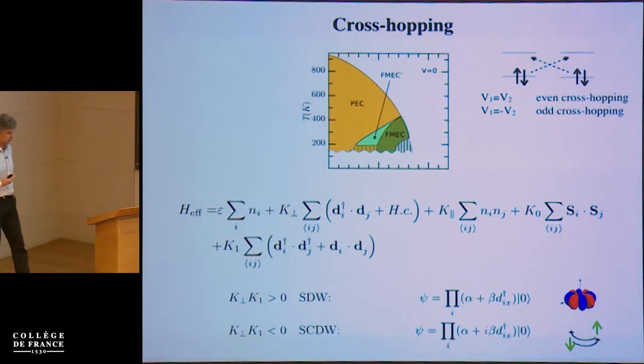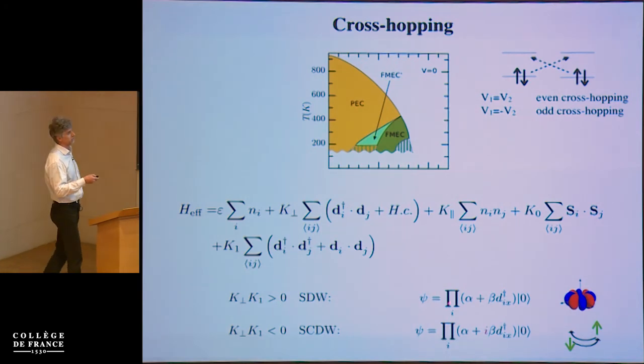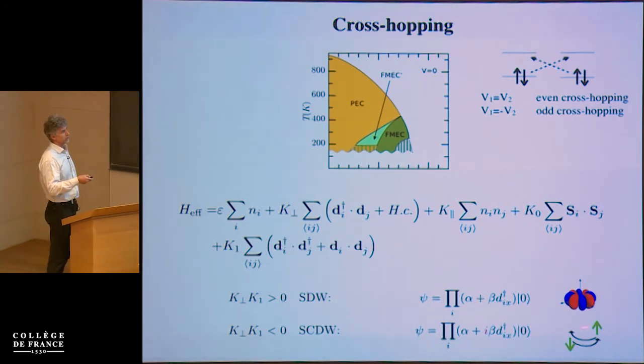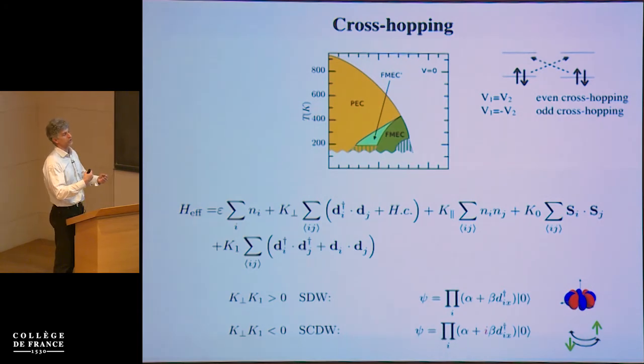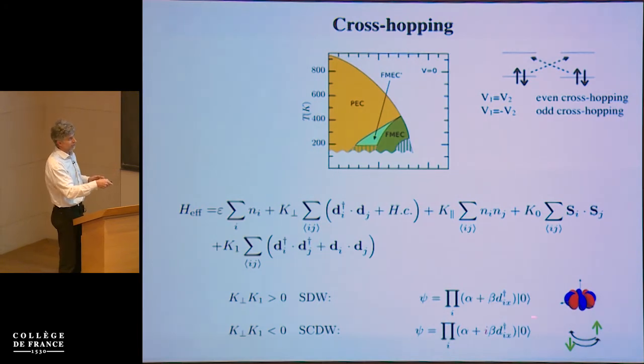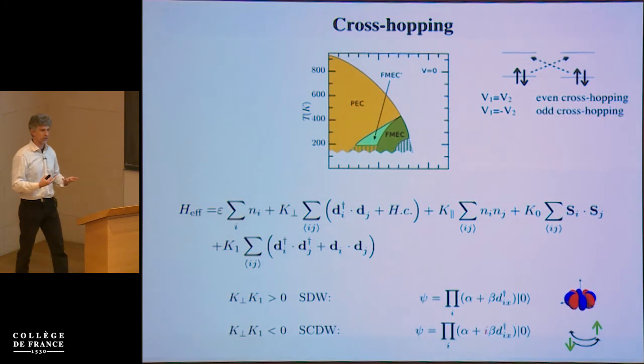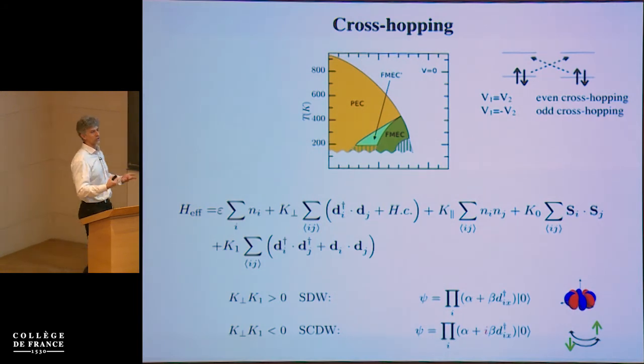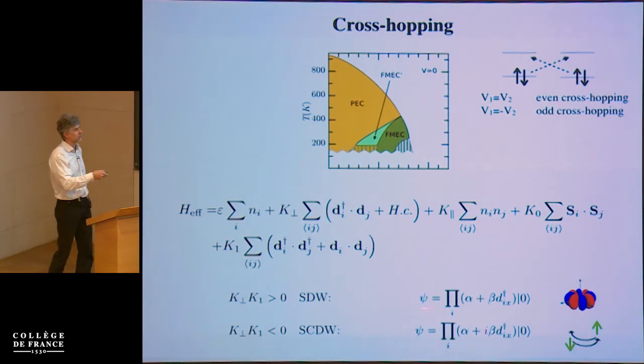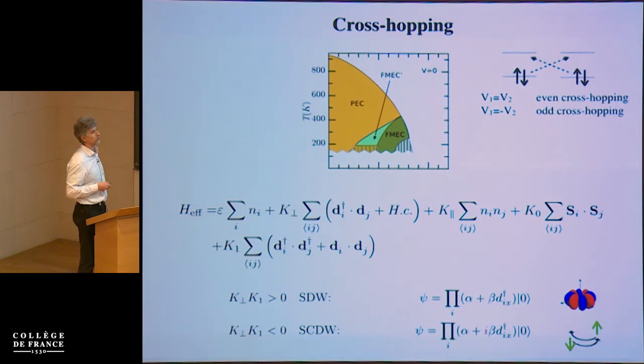So now what is the physical significance of this? If you have a real order parameter, you can show that your ordered state breaks time reversal symmetry, and it corresponds in real space to some multipole ordering of magnetic multipole spin order. The exact shape of your spin polarization in real space, of course, depends on your orbitals. But for example, if you use the x squared minus y squared and xy orbitals, this kind of order parameter would give rise to this spin distribution around each site.